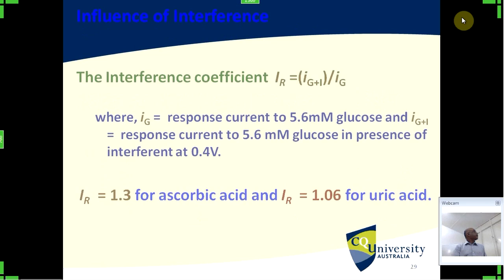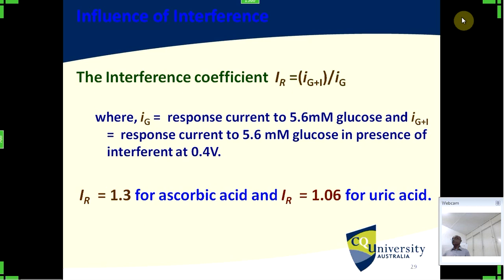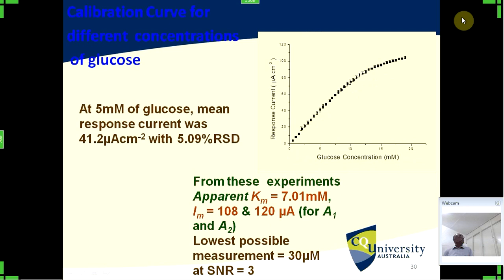Then in the next step, we need to check the sensitivity or the signal to noise ratio of this one, and the selectivity of this sensor for other things. If it responds to, say for example, ascorbic acid or uric acid, which are common components in your blood, that will give you an erroneous reading. So when we plot it, this is the calibration curve. I'm not going to explain all these terms. This is called the Michaelis-Menten constant. 7 is a very good value for a biosensor. So it's again within the acceptable range.